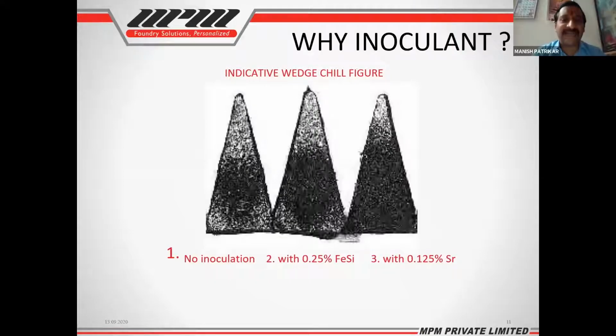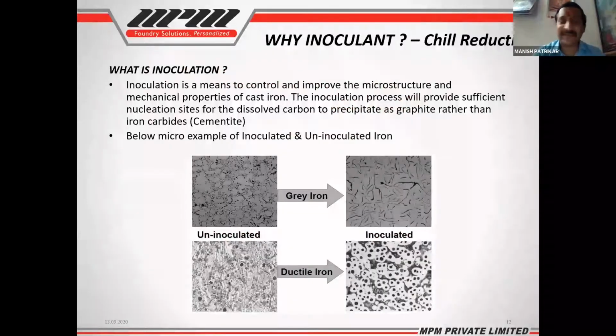If you see in the first slide, you have a higher chilling tendency. In the second slide, because of using ferrosilicon, you have a lower chilling tendency. And in the third chill, because of using the strontium based inoculant, you have a very low chilling tendency. This is already shown by Mr. Gaikwad. You can see on the left hand side the effect of uninoculated microstructure, the first one is a gray iron and the second one is the ductile iron. In the first one you can see the carbide formation, and in the second one you can see the better microstructure for the gray iron as well as the SG iron.